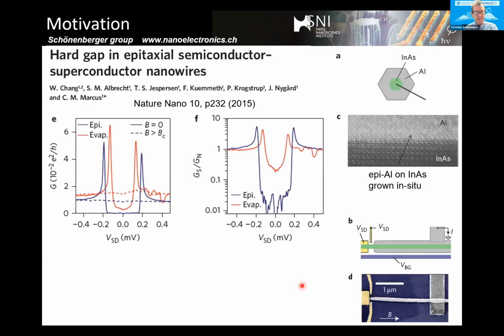Okay, so there is an interesting paper here, which is still a question mark for me. It is this often-cited paper on the hard gap, which we have also seen this morning already. It says that if you use aluminum-coated indium arsenide nanowires, where the aluminum is grown ex situ, this is the red curve, then the gap suppression which is found is kind of soft. And if you use in situ grown aluminum, which grows epitaxially onto the indium arsenide, then you get much harder gaps. So it's quite interesting.